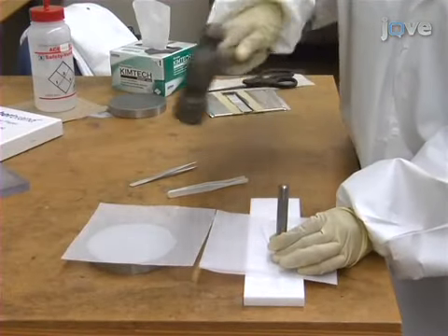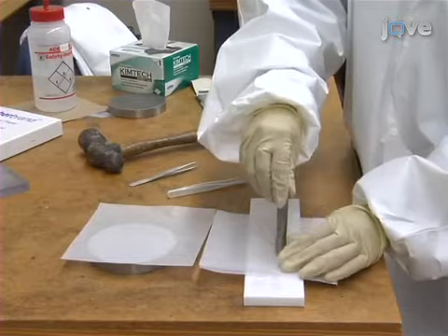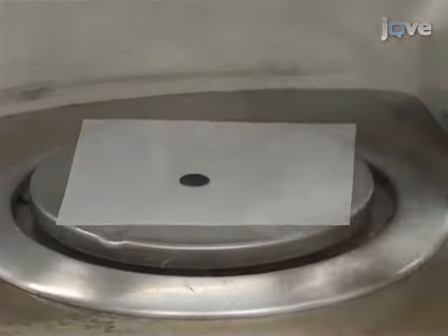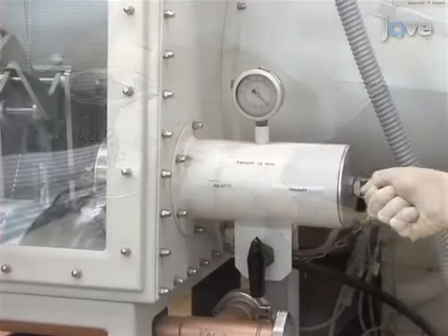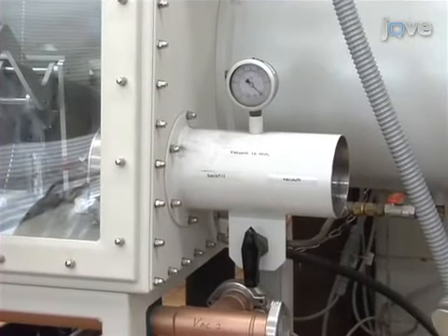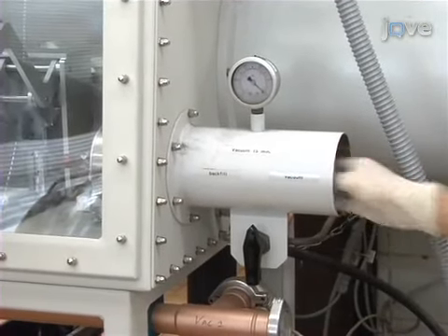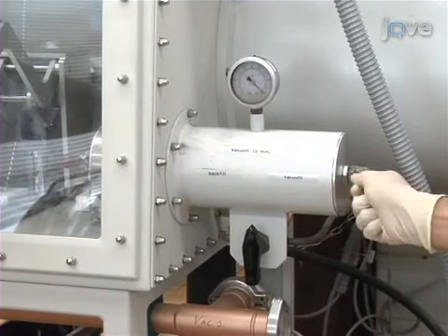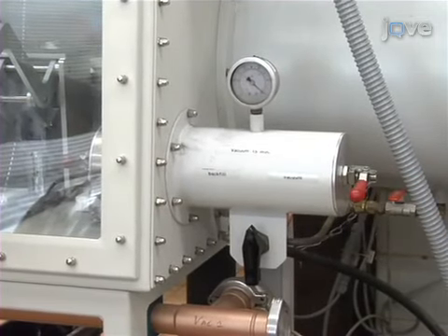Now, punch 8 mm discs of the dried, coated metal foil. Next, weigh the cathodes, wrap them, and place them into the glove box. Also, punch 8 mm discs of the uncoated metal foil of the same material and weigh them.